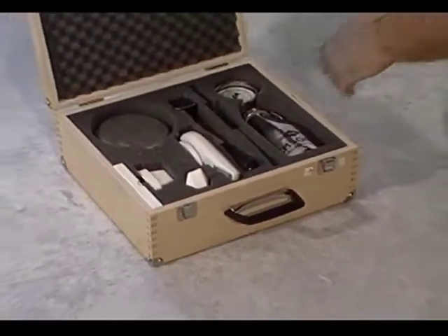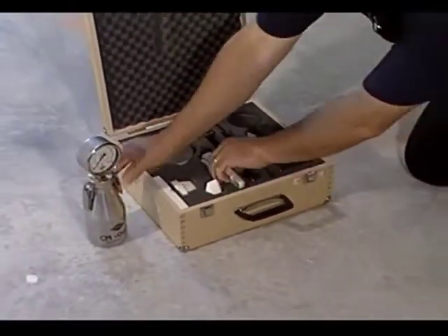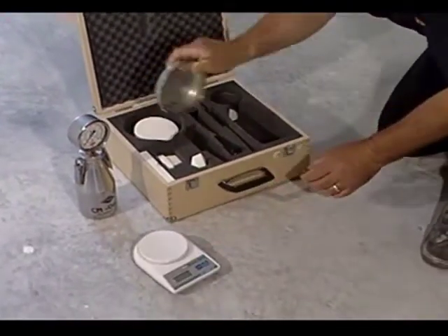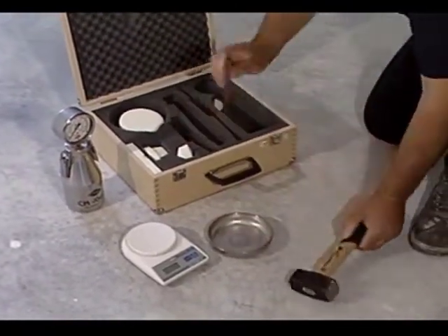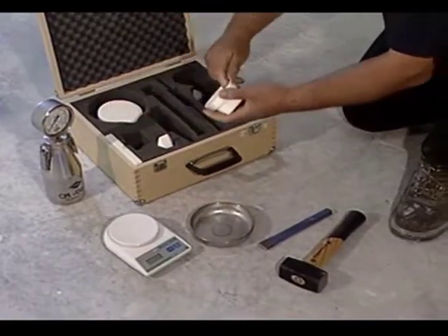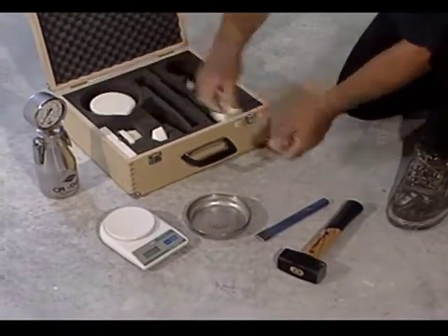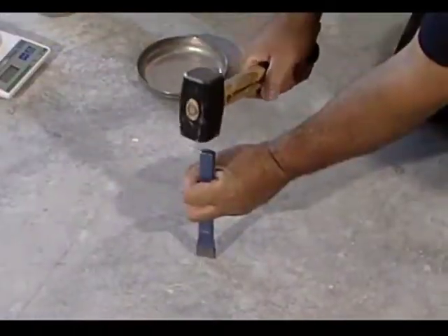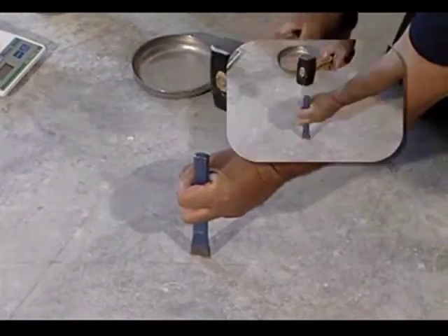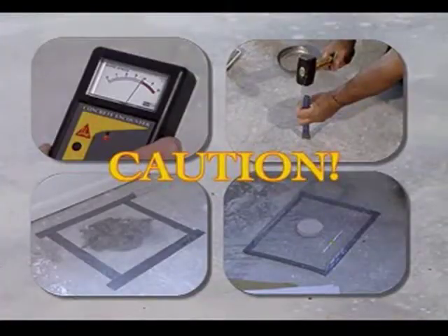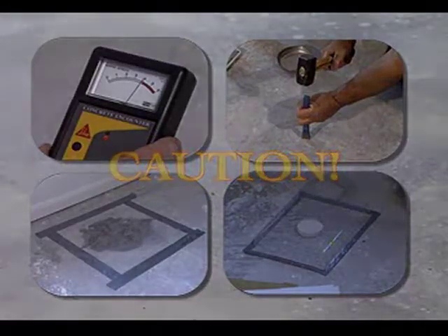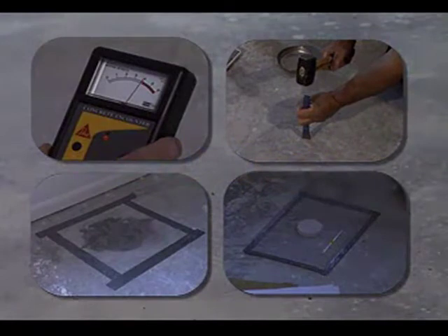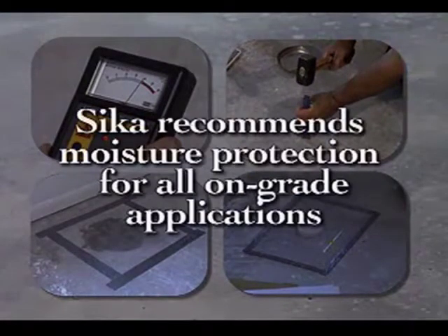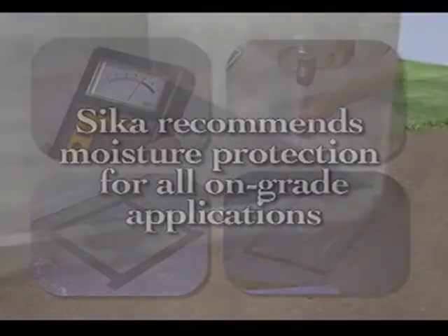The fourth method, Calcium Carbide Method CM, requires taking a sample from the bottom of the screed. This method is used to measure the amount of excess water in the slab and will determine the moisture content. Any reading below 2.5% is acceptable. Caution: these tests only tell the moisture condition at the time of the test. These conditions can change constantly from season to season. Therefore, Sika recommends moisture protection for all on-grade applications.